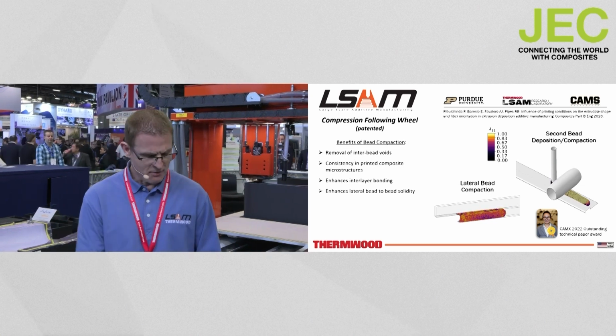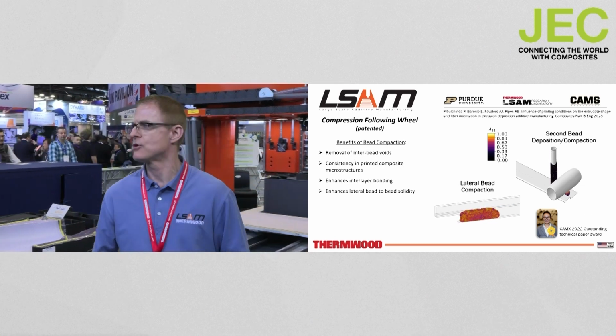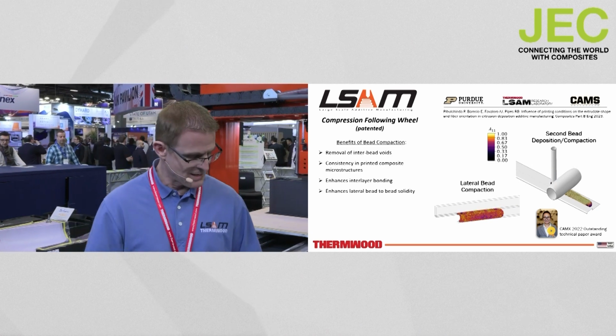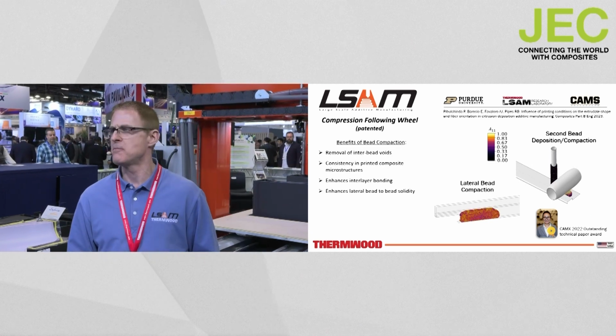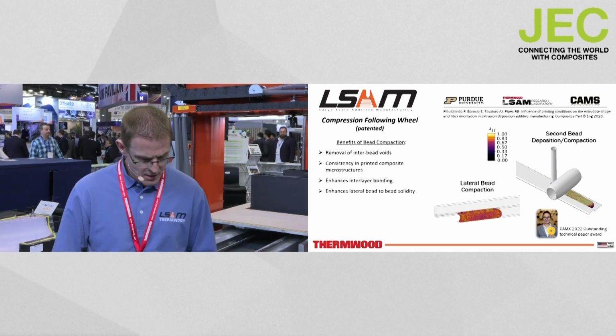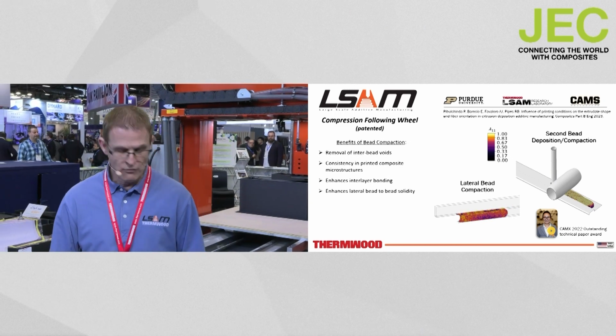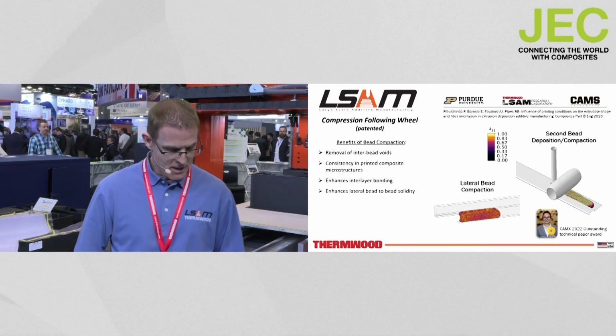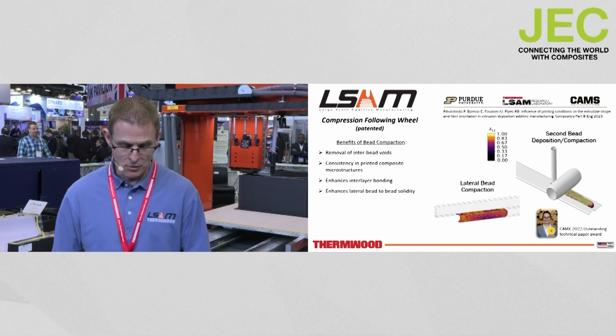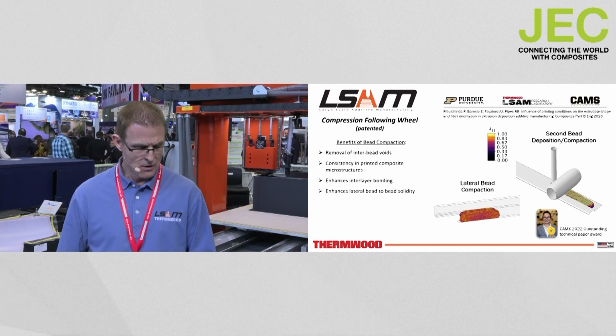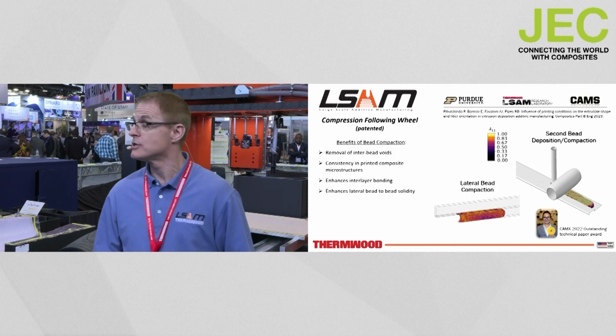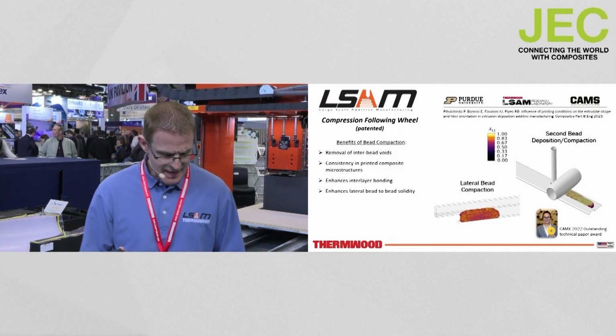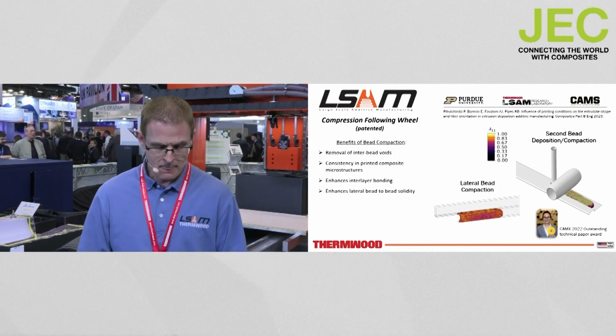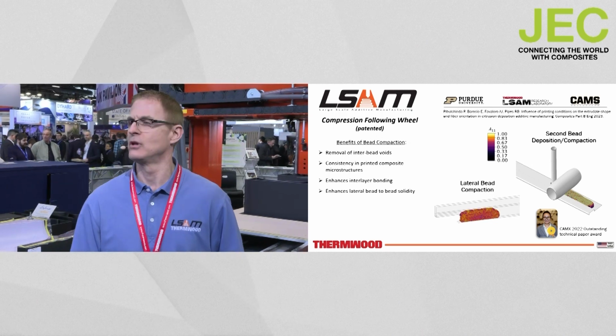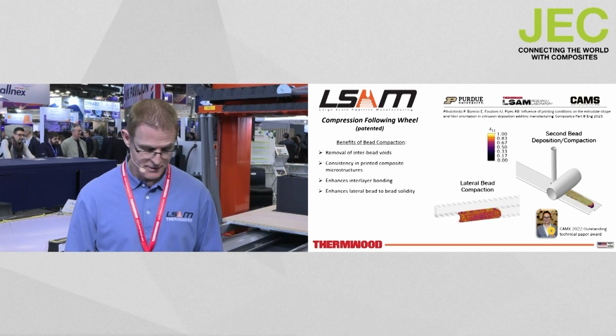In fact, a study performed by a group at the LSAM Research Laboratory further emphasizes the benefits of active bead compaction. Bead compaction aids in the removal of interbead voids. It improves consistency in the printed composite microstructure, which includes repeatable fiber orientation. It enhances interlayer bonding, and it provides the best results for lateral bead-to-bead solidity.